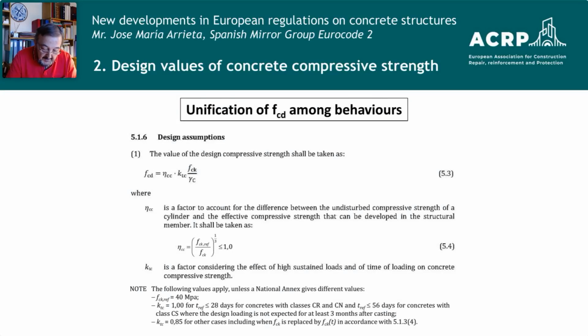After, we convert this compressive strength into the undisturbed compressive strength of cylinder, that means in plain concrete, cylinders with plain concrete without reinforcement. That conversion is made by gamma C, which takes into account not only the uncertainties of the material and geometry, etc., but also this coefficient of conversion. So fck divided by gamma C is the undisturbed compressive strength of cylinder. Now we are going to do another conversion, to convert this resistance into the effective compressive strength in the structural member, I mean with reinforcement.